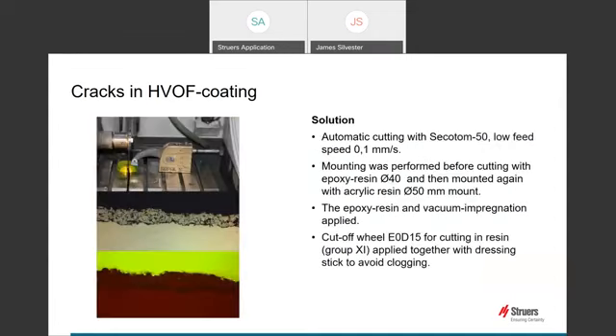When cutting small samples, it is very difficult to obtain consistent low feed speeds. With samples this small, the resistance offered by a small sample will be so low that cutting slow enough in a controlled manner is almost impossible time after time. Part of our plan was to have a robust process that can be carried out repeatedly with the same perfect outcome. Variability is not an option here, as the wrong result can cause ripples in the production line, causing delays and lost revenue.